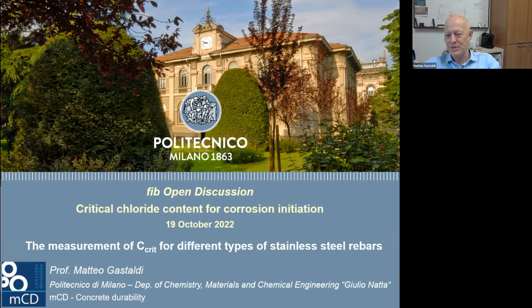Okay, I start to give the answer to the first question, and I agree completely with your comment because it's logical. So if you add chloride, you have a very fast setting and hardening of concrete. And this is a strong problem during the test, during the casting of the sample. For calcium chloride, the problem is incredible. So generally, we use water that is maintained in the refrigerator in order to reduce the effect. First of all, we mix the chloride in water before the period that we maintain in cold condition the solution. So we have a solution with very low temperature, around 5 Celsius degrees. This helps us to reduce the problem related to setting.